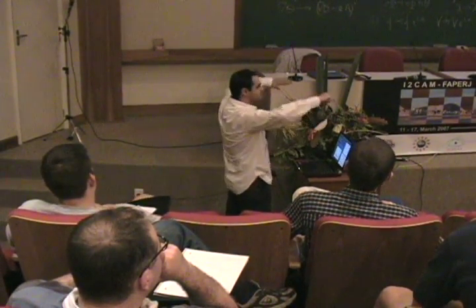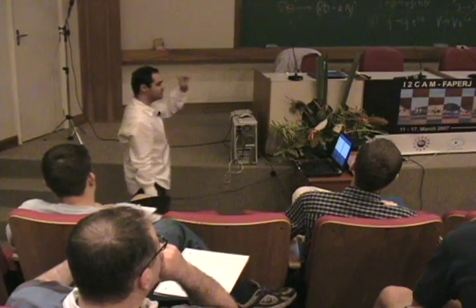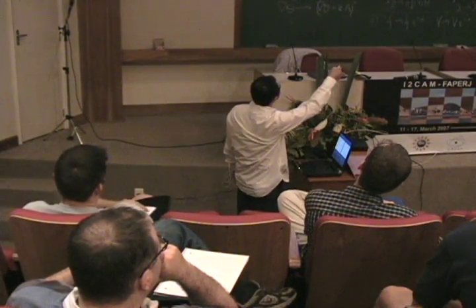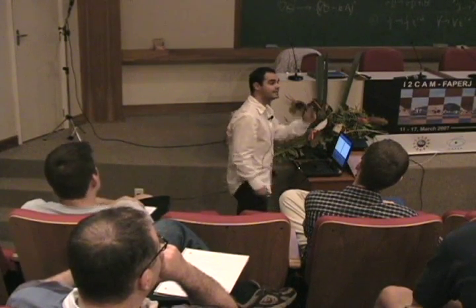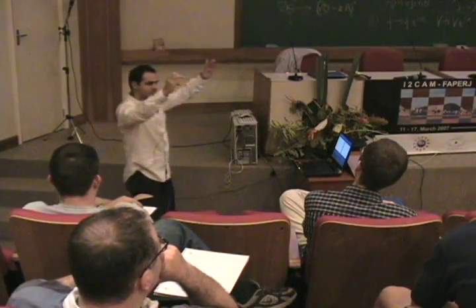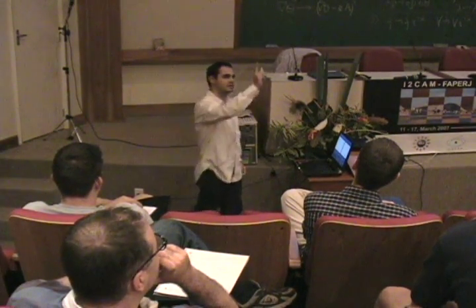But when you dope it in lanthanum, you can see here that the lines get broader very fast with doping. But I can't get information even for the concentrated gadolinium compounds. Look, I have gadolinium indium 3 and the 218s and 115. And again, the sequence in which this linewidth is getting broader is the same sequence that we saw for the splitting of the Gamma 8 and the increase of T_N of neodymium.